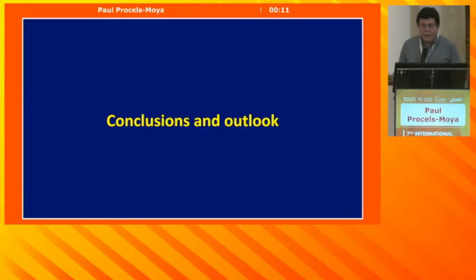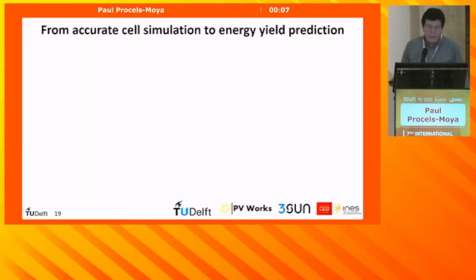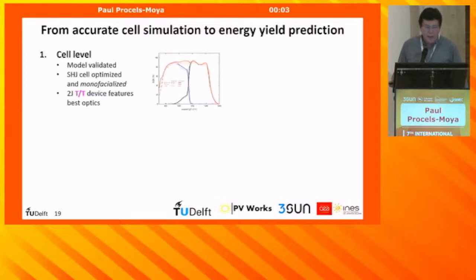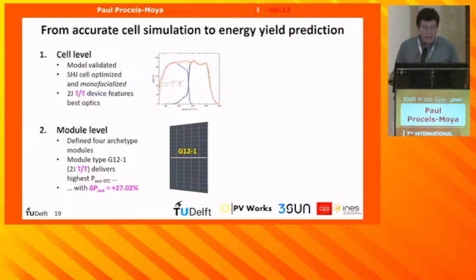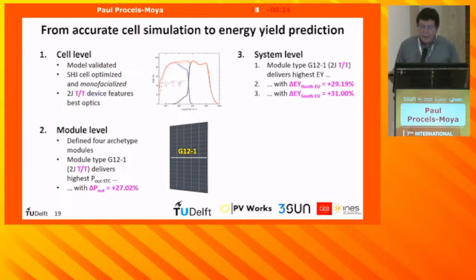With this, I arrive at the conclusions of this study. We are able to go from accurate simulation to energy yield prediction. We evaluate cell-level devices, silicon heterojunction optimized. With this information, we go further for monofacial and two-terminal tandems. We evaluate module levels with the different archetypes. We found that the power output was a massive improvement, capable of achieving even over 27%. And from the system level, we observed results for module types. G12.1 should be the most promising. The texture configuration for module and system level delivers the highest energy yield: for the northern part, about 29%, and for the southern part, 31%.